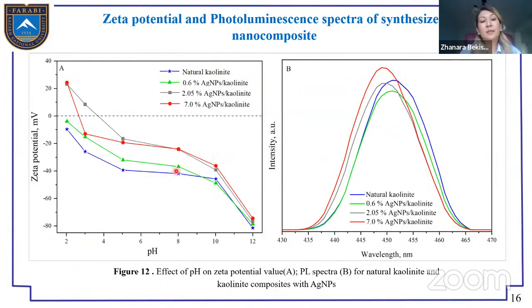The effect of the zeta potential depends on the pH. You can see some stability; it is more stable at pH 4 and pH 11. For the photoluminescence, there are some peaks for natural kaolinite and for the composites obtained at different concentrations, and the peak at 445 can indicate the formation of silver nanoparticles from 15 to 25 nanometers.